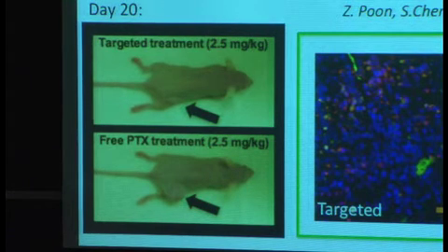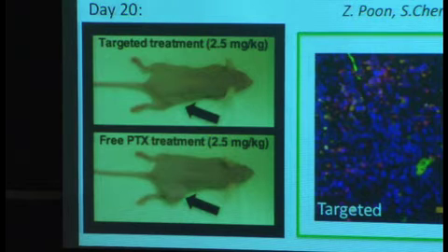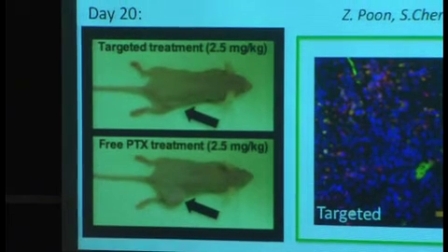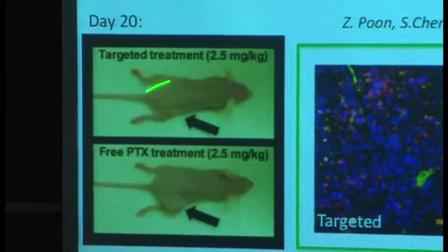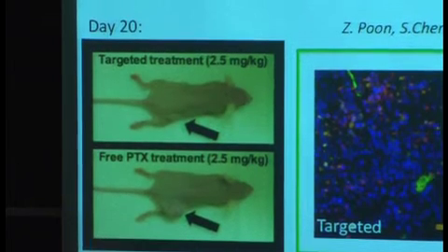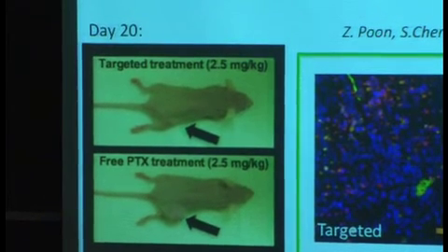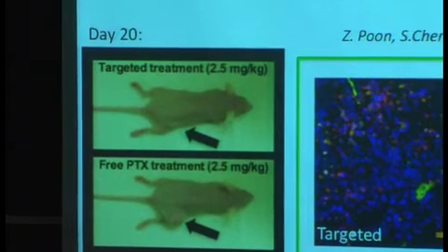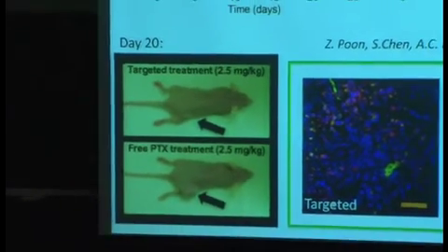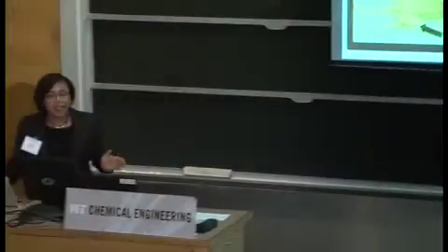We've also done cytotoxicity studies with these systems, and we found about 2 orders of magnitude lower cytotoxicity in our targeted system compared to the free paclitaxel. So we're continuing to examine this. We're very interested in using these concepts of molecular design to further these systems.